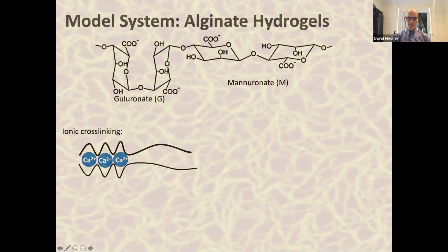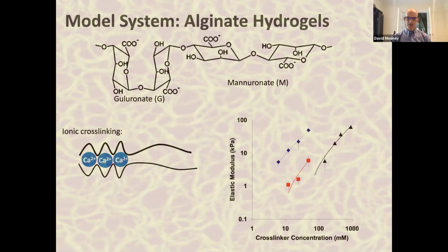Now, one can readily take these materials and manipulate their cross-linking, their molecular weight, the solids content, all the typical tools in soft matter to create hydrogels of varying mechanical properties that we could then use to put cells within and probe how the mechanical properties varied the cell behavior. And some examples of this are shown in this curve on the lower right. Now, the background here is actually an AFM image of one of these hydrogels. So you can appreciate the individual polymer strands, and you can appreciate that these gels are nanoporous, about 98% water, where you have water filling these spaces between the polymer strands. And the cells then would be encapsulated within this nanoporous gel.